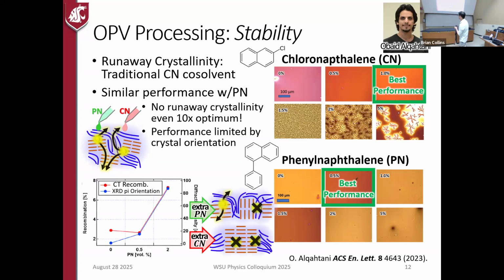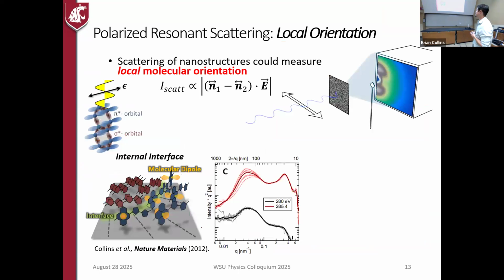And to spare the details, we found, though, through XRD texture measurements, that the crystal orientation was correlated with this CT state separation efficiency, suggesting that something about the orientation of these molecules is potentially affecting the charge generation in these devices. And so we want to look more now at the orientation of the molecules. And that's what I mentioned before. Through the resonant polarization of the X-ray, we can have access to that. And so that's what we've been focused on: can we measure orientation of these molecules?